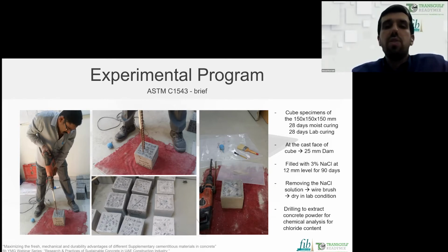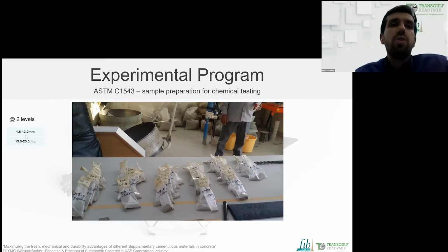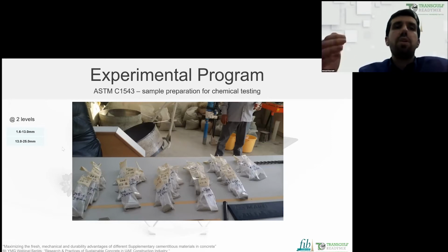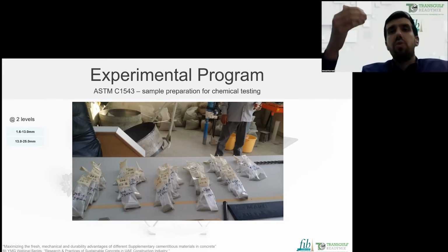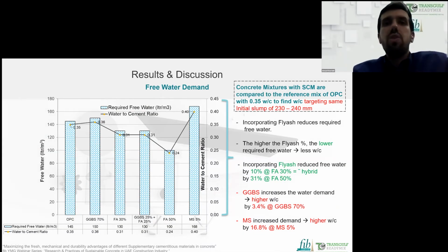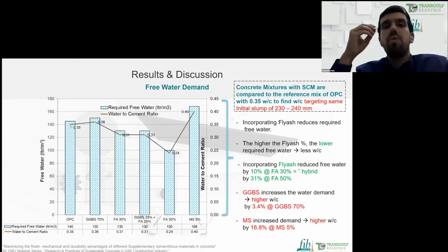And a dam was created at the surface of the concrete, at a depth of 25, and the surface was subjected to sodium chloride solution at the top for a thickness of 12 millimeter for 90 days. And then after that, it was dried in the laboratory and drilled through 2 layers of the material. You can see that the drilling happened to take two different samples of the powder from the concrete and send them for chemical analysis at 2 different levels. One level is between 1.5 and 13 millimeter, and the other from 13 to 25 millimeter, to see the penetration and the concentration of chloride through the different levels in the concrete. See how permeable the concrete is, or how much the chloride can penetrate through it.